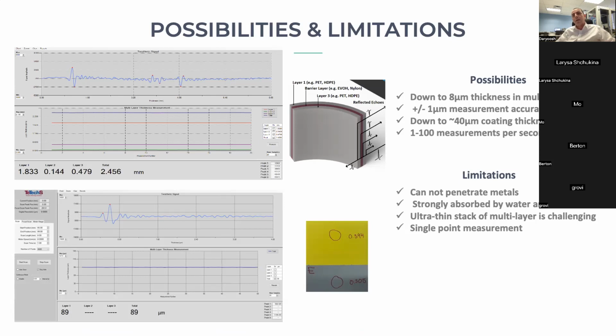And in terms of the measurement speed, between 1 to 100 measurements a second is possible with such a system. In terms of the limitations, obviously, it's light that cannot penetrate metal, so you cannot measure a metal layer or a metal thickness with this technique. It gets extremely strongly absorbed by water and water moisture. So that's another limitation of a terahertz-based system. For example, a living cell, which has a lot of water moisture, you might not be able to penetrate through it, or parts and samples that are highly moist could be difficult to measure.